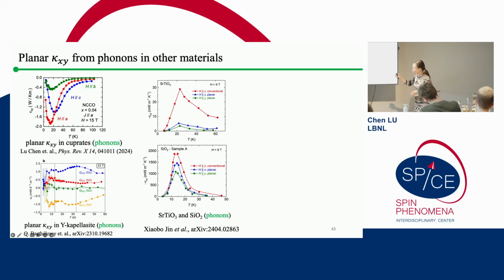For example, Professor Shi Yanli's group in China even found a non-zero planar thermal Hall effect from phonons in some non-magnetic materials, like strontium titanate or copper oxide. For copper oxide, people probably think it's a more trivial type of material, and it doesn't have all these weird competing orders or magnetization inside, but they still saw a very large signal.